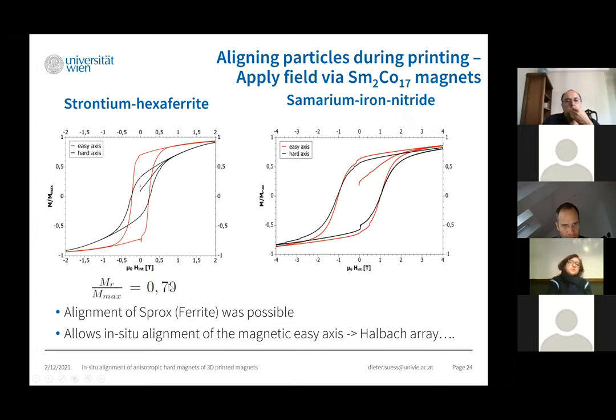This enhancement, MR over MS, is about 0.7. In a perfect Stoner-Wohlfarth ensemble of non-interacting particles with random orientation, it would be exactly 0.5. So we see a clear enhancement of the remanence. You see this 0.5 also here, which is the situation when you don't have an aligned magnet.